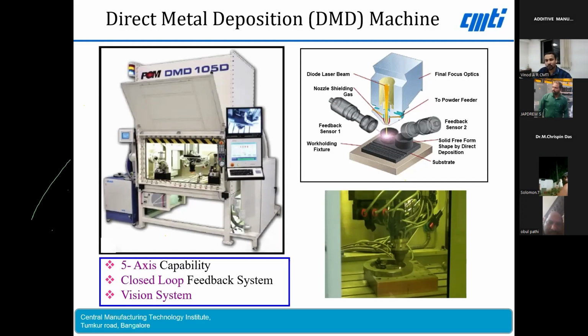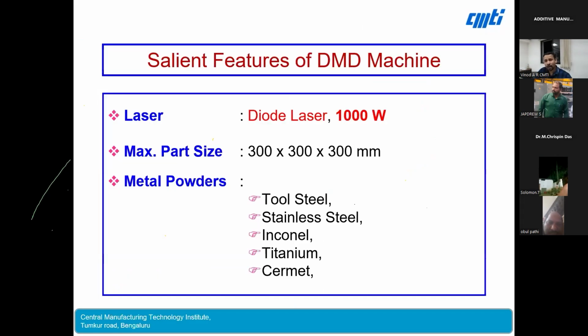So with this machine, you have a 1 kilowatt laser. Basically, the part size is around 300 by 300 by 300, actually all XYZ 300. You can process most of the materials like different types of tool steel, stainless steels, Inconel, and titanium-like materials also can be processed.